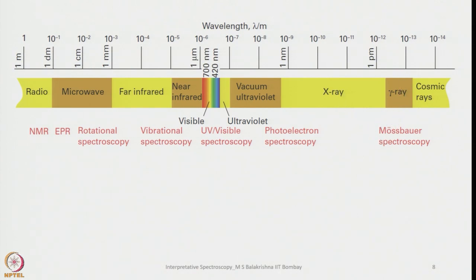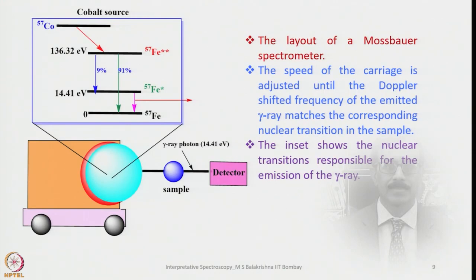We use gamma rays. Then this is a typical layout of a Mössbauer spectrometer. Here the cobalt source is there, as I mentioned, 57Co is considered and it is put into steel. The speed of the carriage is adjusted until the Doppler shifted frequency of the emitted gamma ray matches the corresponding nuclear transition in the sample. The inset shows the nuclear transition responsible for the emission of the gamma ray here. And then, of course, it comes to the sample, then goes to the detector.